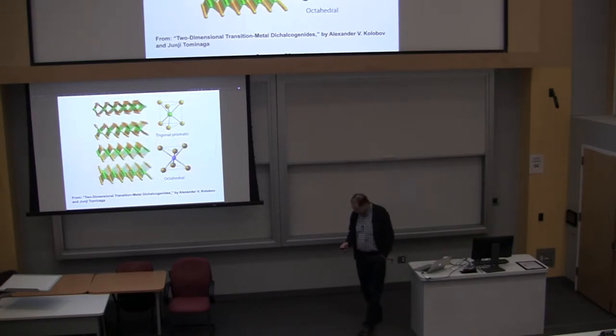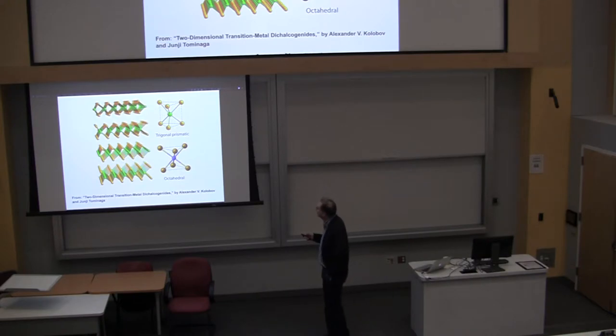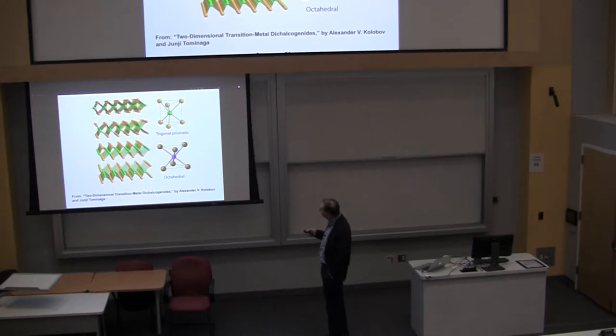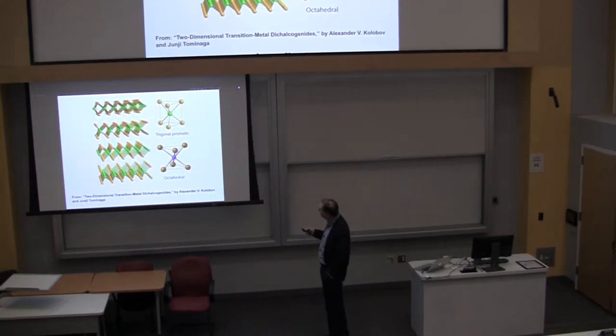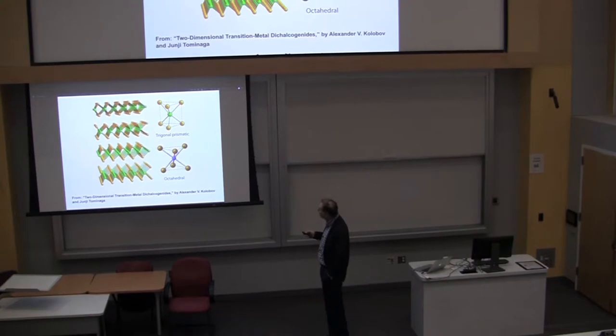So the basic idea is that you have a layer of metal atoms, and then a layer of chalcogens, and you've got what is called a van der Waals gap. Technically, the bonding isn't truly van der Waals, but it's very weak bonding. When you cleave these materials, you cleave them between the two sheets here, and it leaves quite nice surfaces. They're usually fairly pristine and well ordered.